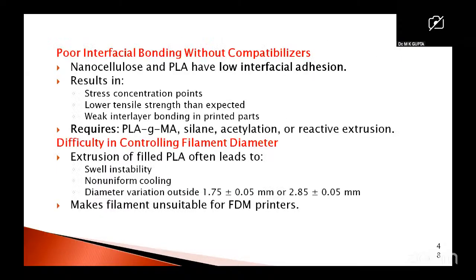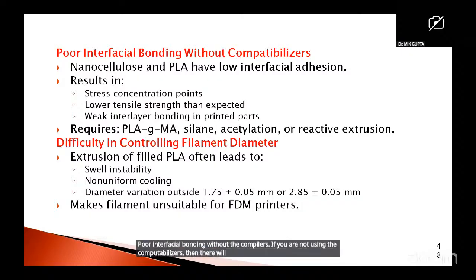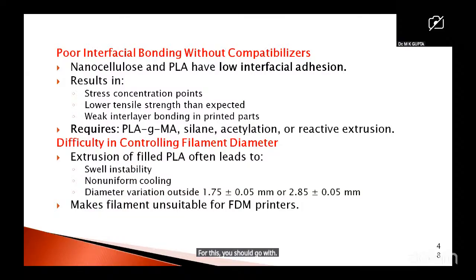Poor interfacial bonding without the compatibilizers. If you are not using the compatibilizers, then there will be poor interfacial bonding of the nanocellulose with the PLA. For this, you should use suitable compatibilizers for strong interfacial bonding between the PLA and the nanocellulose.